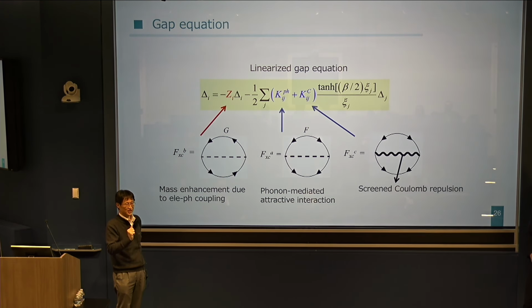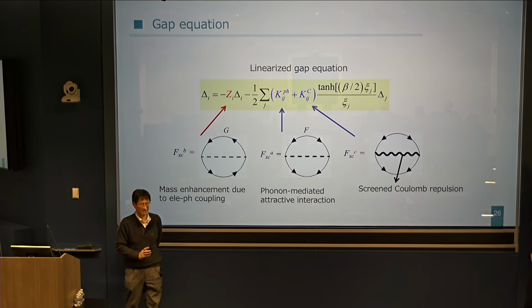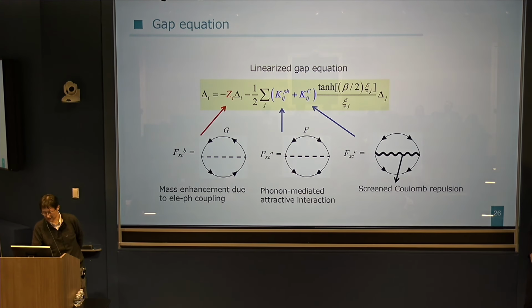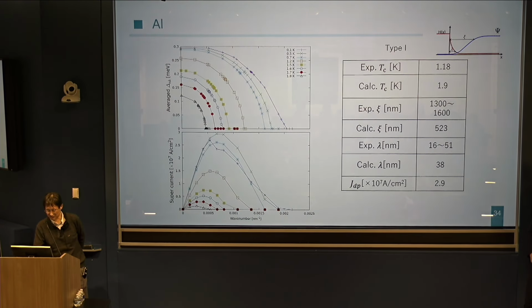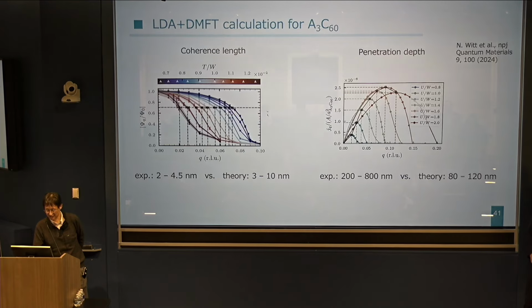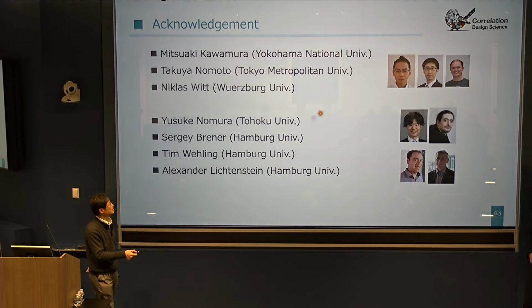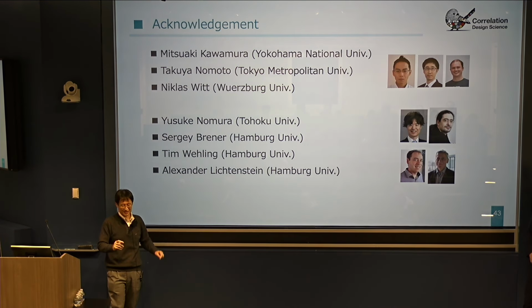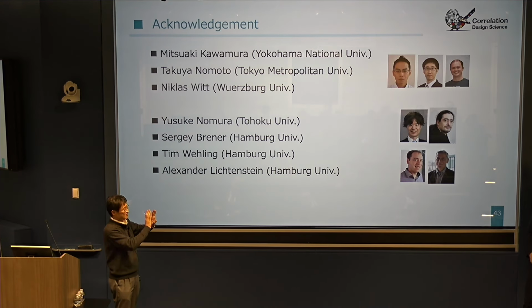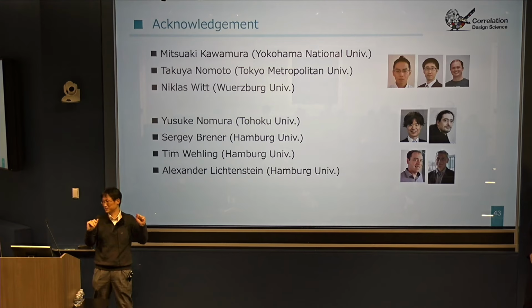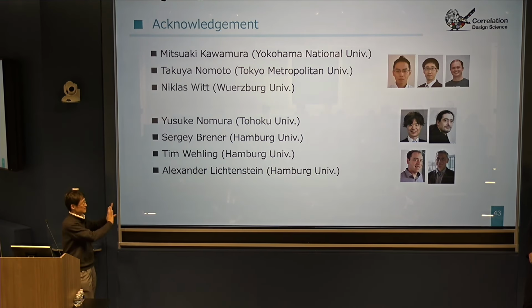And the numerical cost to solve this gap equation is much cheaper than the standard Migdal-Eliashberg equation, because there is no frequency in the equation. And so that is a good thing when we think about performing a high throughput calculation. And in fact, my collaborator, Mitsuaki Kawamura, performed the high throughput calculation for elemental metals, and he made a list of calculated Tc and compared the theoretical Tc and experiment, and the agreement between theory and experiments is basically very good.